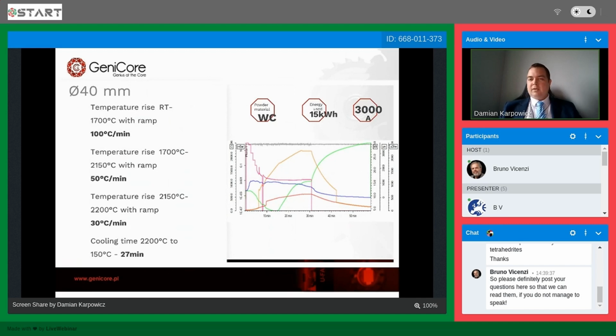So 3 kiloamps is enough for us to sinter 40 millimeter tungsten carbide, as you can see here, even with very high heating rates, which is 100 Celsius degrees per minute. And of course, we achieved full density. So we can sum this up: this small device is all that is necessary for R&D institutes to work on small samples, to hopefully scale it up in the future.